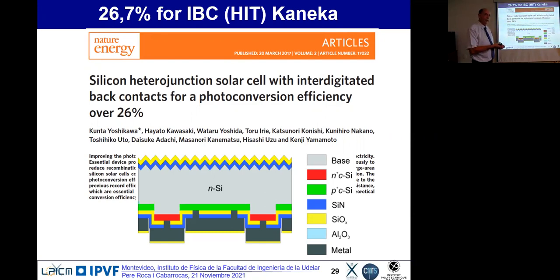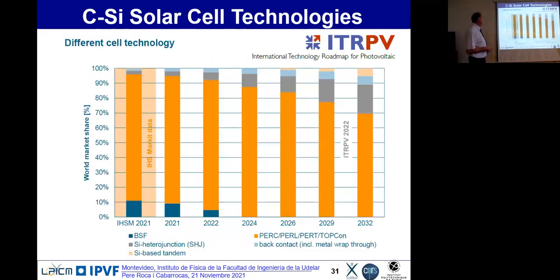There is mechanical shadowing. In the lab, we are using plasma processors, with which you can do localized deposition. There are different approaches. So here we are. So what is the roadmap? Aluminum back surface field. This is what allowed the industry to take the growth from 100 megawatt to gigawatts. But this technology is over. Aluminum back surface field is over. Now we have passivated contact solar cells. And this will go on. And you see that something is coming up.